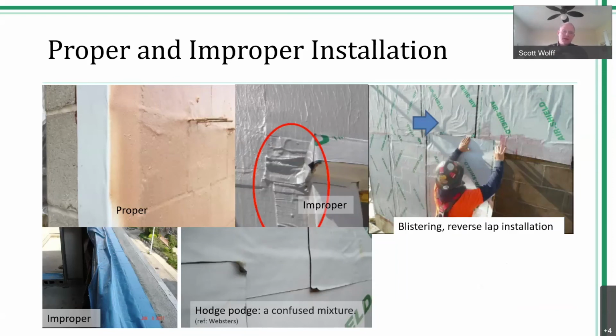It is important also to point out that in some instances, not every project, every once in a while, this high density polyethylene carrier film is so dense that if we fully cover this with a liquid air barrier, every once in a while we'll experience some alligatoring or cracking. And I've seen this on a number of projects where the project team shut the job down because they thought the air barrier was failing. Well, they didn't realize or didn't make the connection that we're already airtight and watertight. And again, manufacturers typically specify 1 to 2 inch overlap to basically seal the leading edge of these transition membranes. So just something to keep in mind. It's not the end of the world as long as we have that connection and we seal that leading edge.